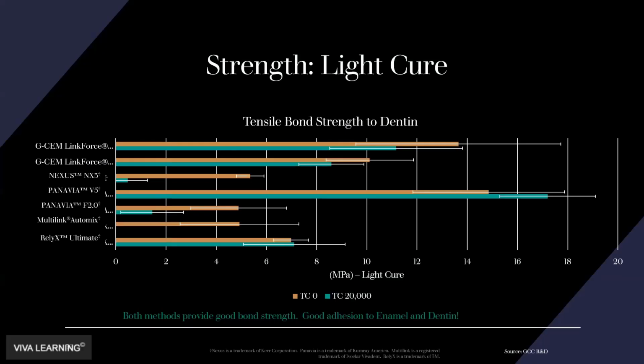When we look at the overall tensile bond strength to dentin, obviously that's less than it is to the actual porcelain itself, but we're still seeing upwards of anywhere from 12, 14, 18, 20 megapascals for the variety of different types of resin cements that we see here from these different manufacturers. And of course, we see that some of these are more adversely affected through these different cyclings. This is showing where these are thermal cyclings 20,000 times, so simulating years of service in the mouth.